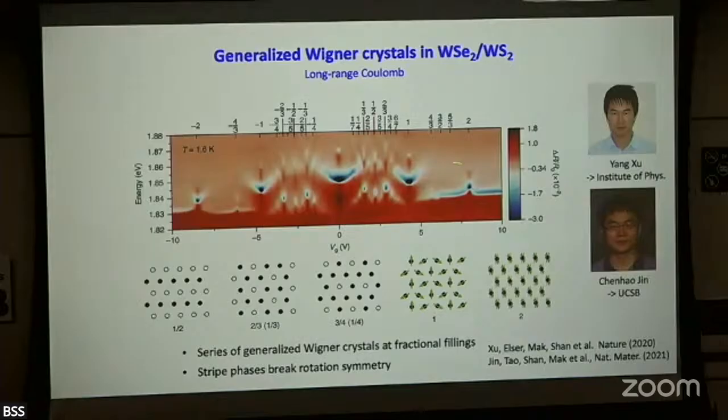You can also see the spectrum doesn't just look like one absorption peak and another absorption peak; if you look at the values, there are some negative and some positive. This is all due to interference effects, because your sample lives in some environment and you have multiple reflections. And this will also change when you change the doping or gate voltage, because the environment changes a little bit. So it's not fully expected that electron doping and hole doping should look perfectly symmetric.